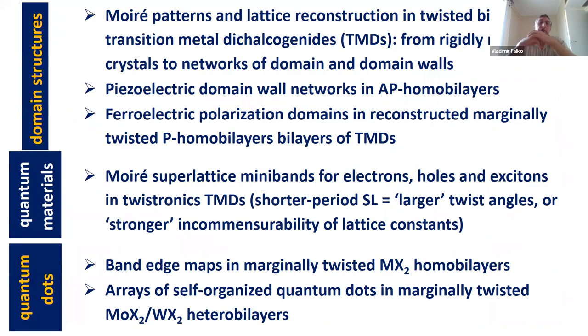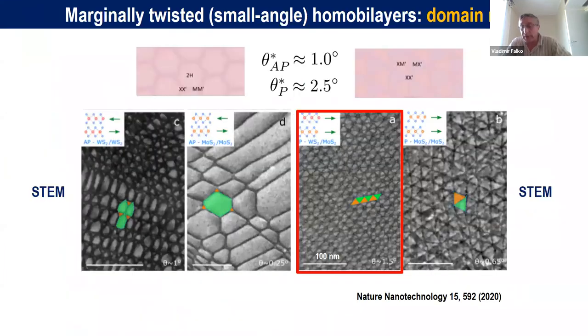And this is where the reconstruction of the crystal starts playing an even more important role, because the form and the nature of, and position across the supercell of, the quantum dots that we're talking about will be strongly affected by the developing deformations, by piezoelectric potential, by ferroelectric charge transfer, and also by the band gap renormalization that takes place in the system. So this is an example of how this looks at the mesoscale, at the distances of many nanometers.